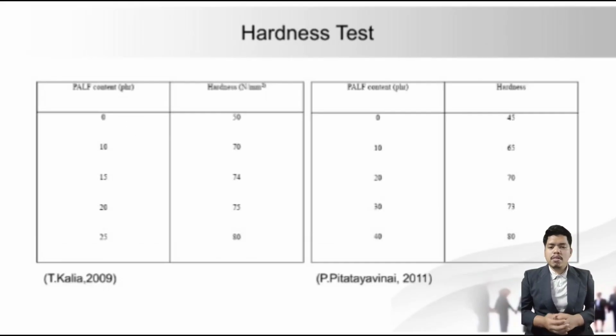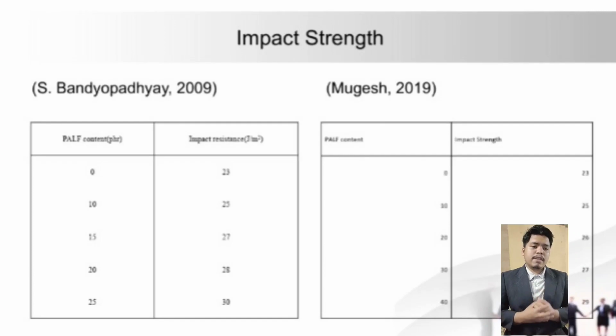For the hardness test, both of the researchers from the table shows that they managed to reach the highest value, which is 80, as the value or the loading of the PALF increased. Okay, so for the impact strength, we can see that if we use a lower value of PALF, it can reach up to 25 joule per meter square. But if we increase the loading of the PALF, we can go much more, from the 25 up to 30 joule per meter. And that is the average value of the impact strength when we use PALF as the composite fiber.